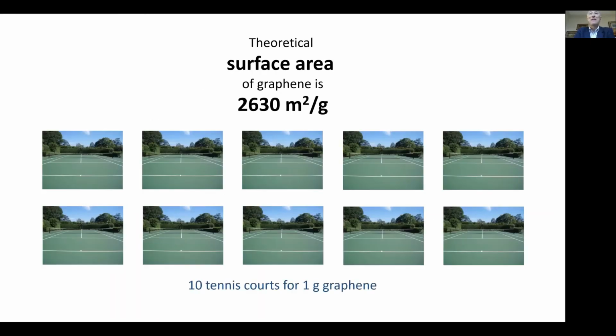Actually, the theoretical surface area of graphene is 2,630 square meters per gram of graphene. That means if you have a gram of graphene and you think about the two sides of a sheet, that's the equivalent of 10 tennis courts of area. I should say that the PIMs I mentioned earlier have about 3 tennis courts of effective area in a gram of the polymer. There's quite a lot of effective surface just in the polymer.